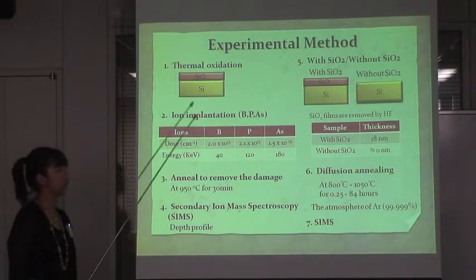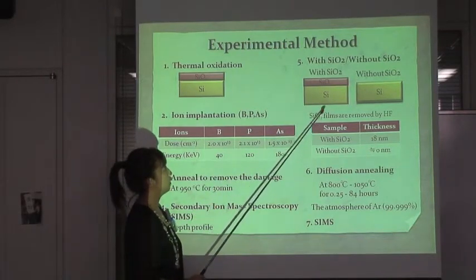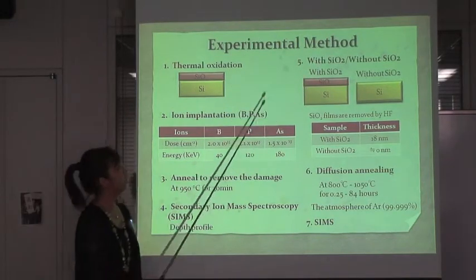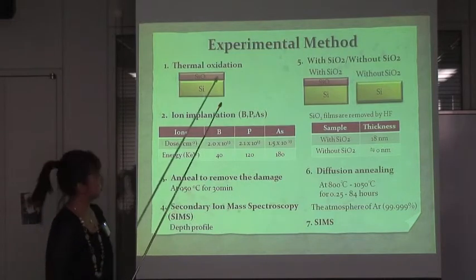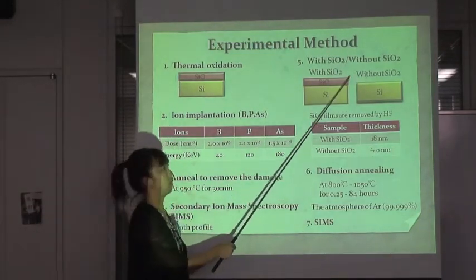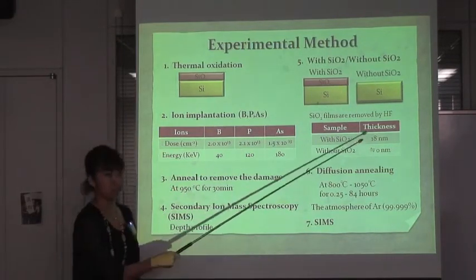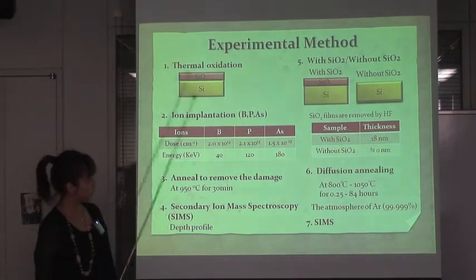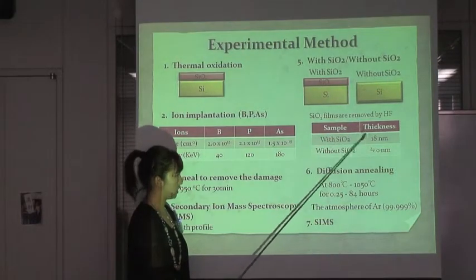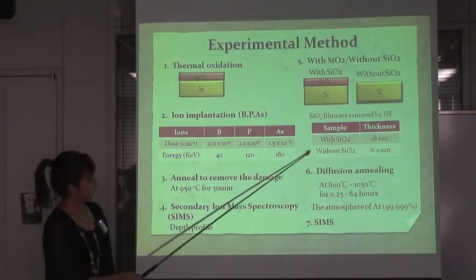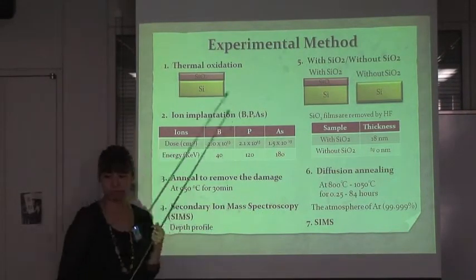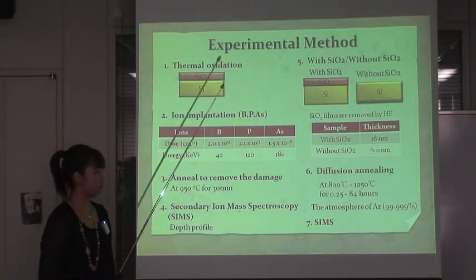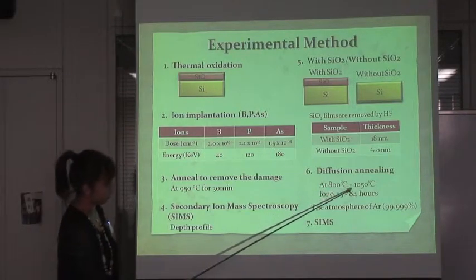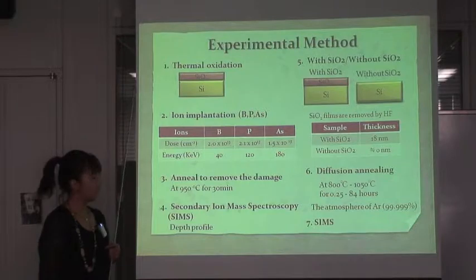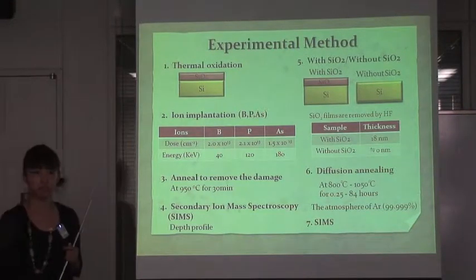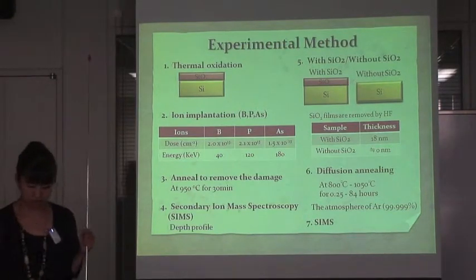And then these samples were separated into two kinds. The one is named samples with silicon dioxide, where the silicon dioxide films were remaining on the silicon surface. And the other is samples without silicon dioxide, where the silicon dioxide films were removed by HF treatment. The thickness of silicon dioxide of the samples with silicon dioxide was, at this time, 18 nanometer. On the other hand, the samples without silicon dioxide had almost 0 nanometer. And diffusion annealing took place for all of the samples at 800 degrees to 1050 degrees for 0.25 to 84 hours in the atmosphere of 99.999% pure argon gas. And then the distribution was measured by SIMS again.